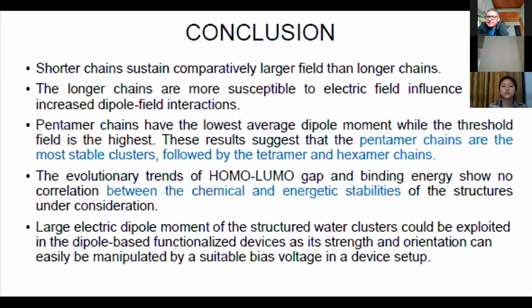And we saw that the HOMO-LUMO gap increases and decreases, but the binding energy just keeps increasing. So there is no strong correlation between the chemical and energetic stability of the system. Also, the systems which we have considered have a large dipole moment, which means this particular feature can be exploited and used in nano-based devices, and this dipole moment can be modulated by using some electric field.